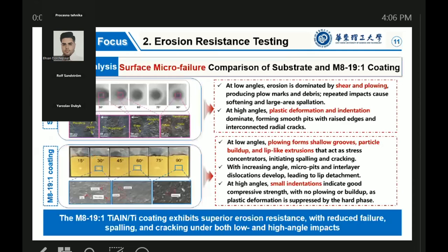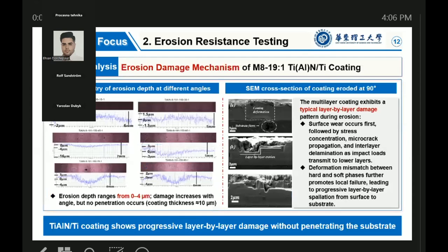And the surface morphology revealed that for uncoated substrates, shearing and plowing dominate at low angles, while indentation and cracking occur at high angles. In contrast, the multilayer coatings effectively reduce material loss, spallation and cracking across all conditions, demonstrating superior erosion resistance. 3D morphology also revealed that coating damage did not reach the substrate.